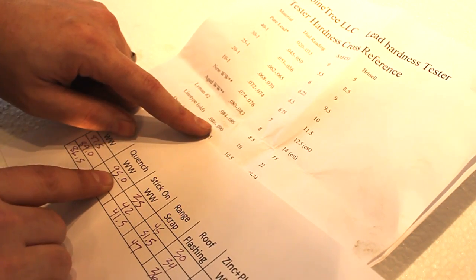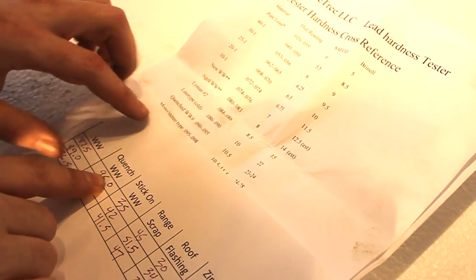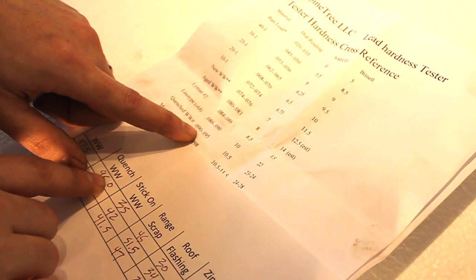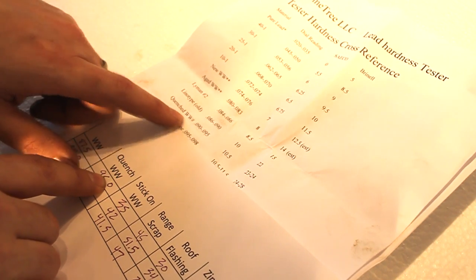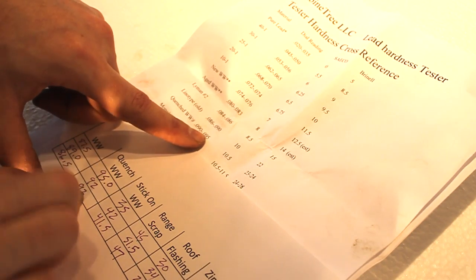Quenched wheel weight: 92, 93, 95. And that seems to fall right here. It says quenched wheel weight would be in the 90 to 95 range, so that seems to be right on.